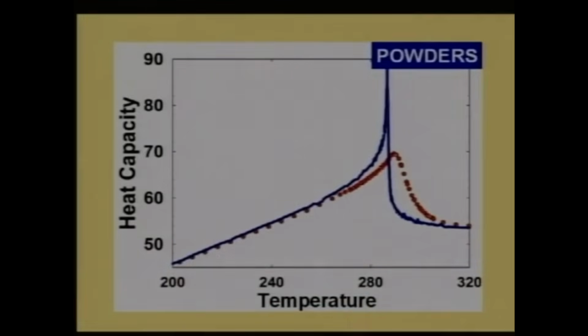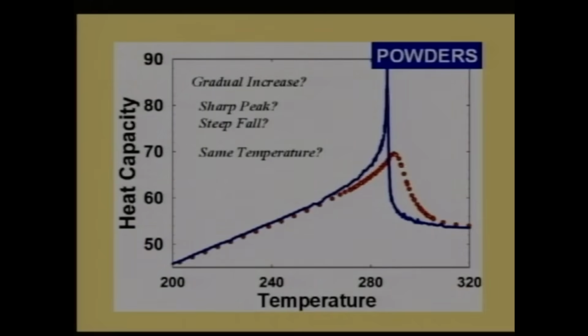The mid-sized particles, the powders, give us some idea. The red curve here presents the powder's heat capacity, while the blue curve is the big crystal data. Compare the key features for the two curves. The low temperature behavior is about the same, but the heat capacity in the transition region rises less steeply, it falls more slowly, and the peak appears at a slightly higher temperature. But overall, the magnetism hasn't changed drastically.